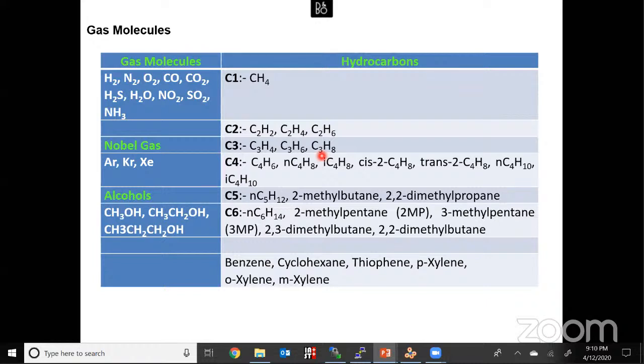So it highly depends on what we want to do with this material. If you want to separate C2 hydrocarbons, you can use different MOFs. For example, if you want to separate ethane and ethylene, by choosing an appropriate MOF with appropriate pore structure, you can selectively trap ethane over ethylene, because when we do separation, we need to keep in mind the kinetic diameter of the gas molecule that we are going to use.